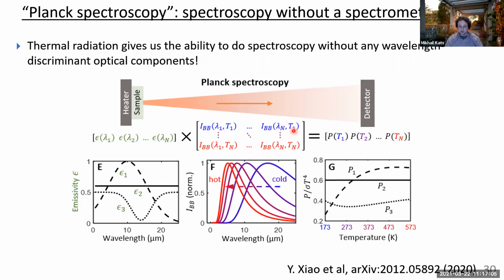It's literally just the matrix of discretized Planck's law. And you know that this emissivity multiplied by this black body matrix is going to be equal to this vector of power versus temperature over here. And so if you know these two things, all you need to do is apply some sort of inverse problem method to get the emissivity.